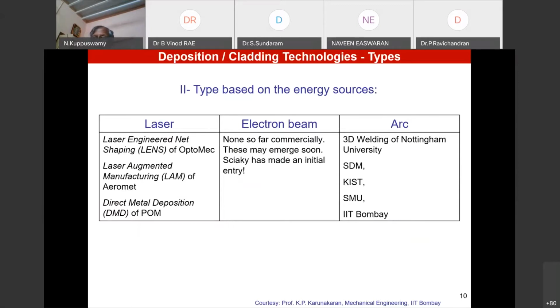Now, I would say in terms of quality, in terms of performance, in terms of running cost, electron beam is the best, provided you know how to use an electron beam. Maybe I'm biased because I used one in my PVD machine for about 10 years. Now, electron beam is used where you have to have a controlled atmosphere. Controlled atmosphere is required when the quality of the deposition has to be perfectly controlled, such as in a medical implant, like a knee implant. Now, arc is also a very good way of doing it. Nottingham, especially, is a pioneer in this area.